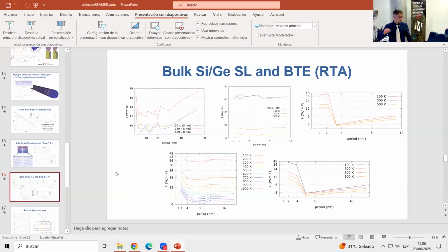Because you have an interface. You need to decide in the BTE if you are assuming inelastic scattering, elastic scattering, or a probability to cross the interface with no scattering, which would be the metamaterial picture. So how do you set the boundary conditions in the BTE to reproduce this minima?